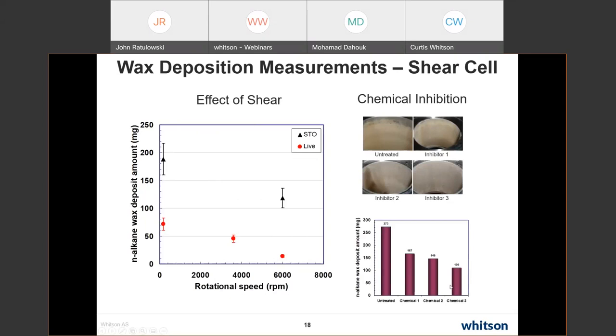And you can look at inhibitor testing as well. You can see here pictures of various inhibitors that were used and the amount of wax that was deposited. And so you can see that the inhibitors do actually reduce the wax deposit, but don't eliminate it, which is pretty consistent with what you see in practice.